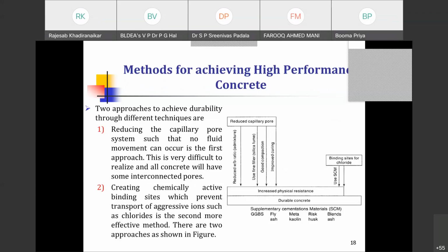As I said, there are two basic techniques that are used for achieving high performance, two approaches basically. One is reducing the capillary pore. As I said, at the microstructure level, this is how HPC or HSC is distinct from conventional concrete. I said that it has a reduced porosity. So reducing the capillary pore system such that no fluid movement can occur is the first approach for achieving high performance. This is very difficult to realize, and concrete will have some interconnected pores. Totally you cannot avoid them, but we can minimize them.